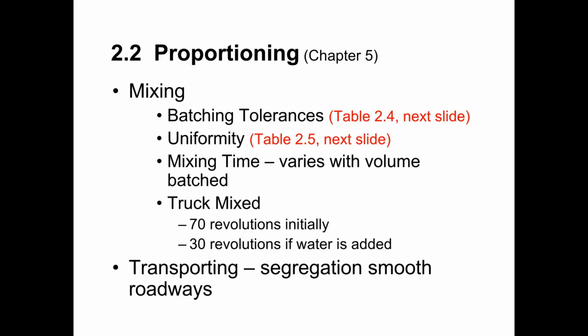So this is one of the reasons why some plants use mixer trucks to deliver concrete to their beds. It's so that they can make small adjustments to the concrete at the bed. There's nothing wrong with doing that. Most of the time, these plants are not using the truck to actually mix the concrete. They're centrally mixing the concrete and then using the truck just to transport the concrete to the bed. But whether the truck mixed the concrete initially or it was centrally mixed initially, if any adjustments are made to the mix at the bed, any adjustments to the amount of water, any adjustments to the admixtures, then that concrete needs to be remixed a minimum of 30 drum revolutions.